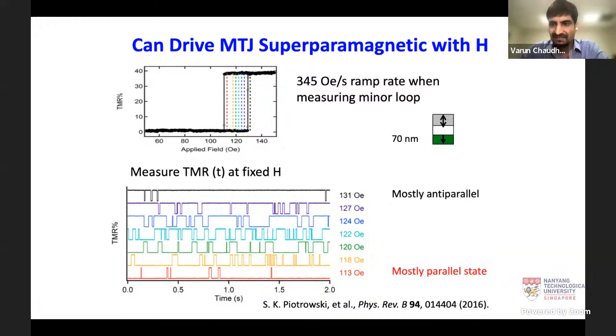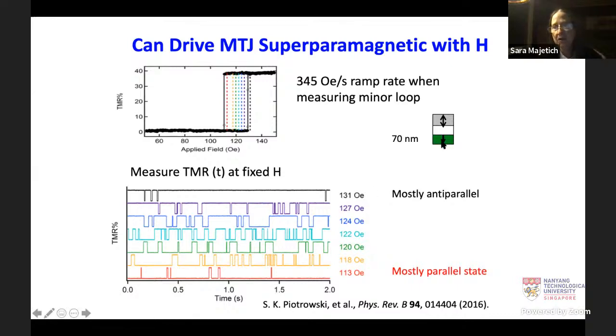Some of our earliest work, we were able to control the superparamagnetism with an external magnetic field. Here we had a perpendicular tunnel junction with the free layer on top, so it could be magnetized up or down, switching back and forth. If you did a hysteresis loop, you would get the black curve. You ramp the field and you see a switching from, in this case, low resistance to high resistance.